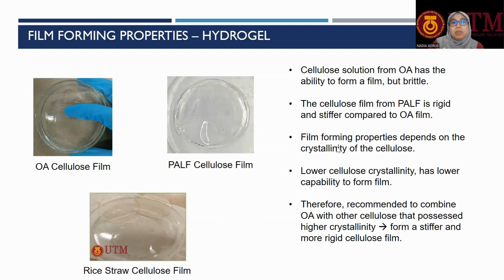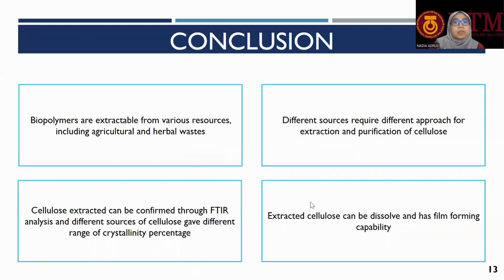So in this case, we can conclude that film forming properties depend on the crystallinity of cellulose. The lower the cellulose crystallinity, the lower the capability to form the film. And therefore, we can also combine different resources of cellulose to have different stiffness and also different properties, like more rigid cellulose film.